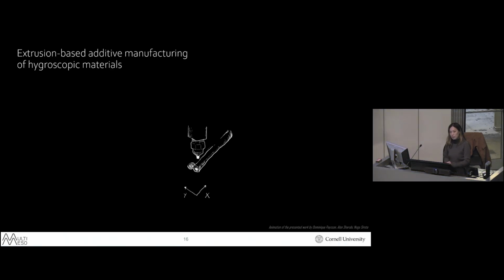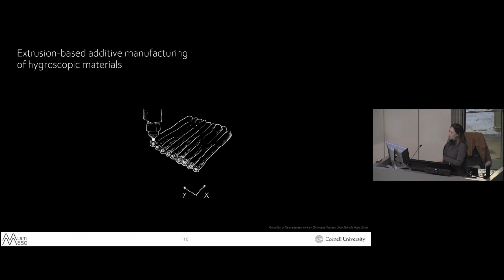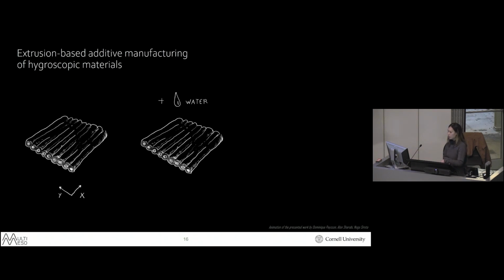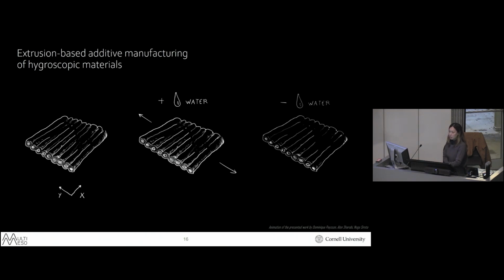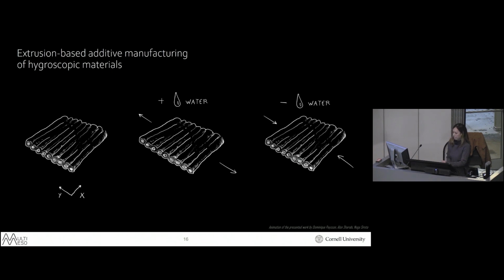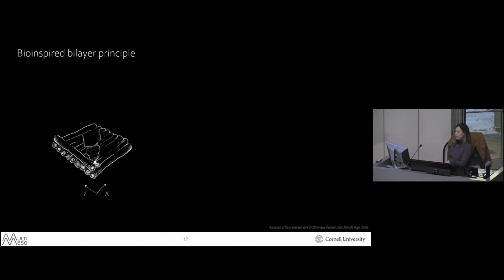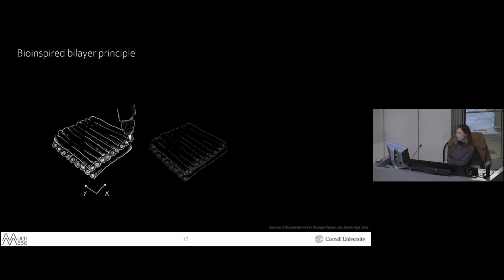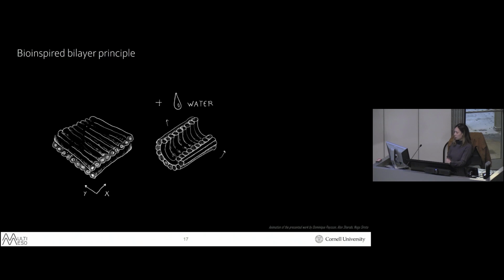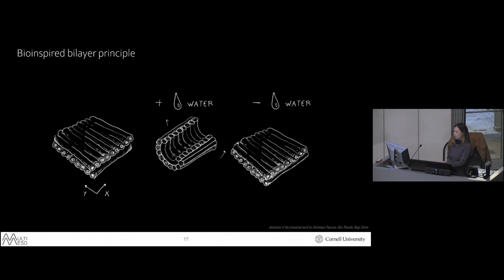So first I want to explain how 4D printing works. Through the process of extrusion, it leaves these anisotropic features on the material layer, which when you print that with a hygroscopic material like wood filaments, swells or shrinks directionally. And by printing a less swellable layer on top of this existing layer, similar to the pinecone structure that we saw earlier, the resulting bilayer bends in one direction when swelling and the other direction when shrinking.